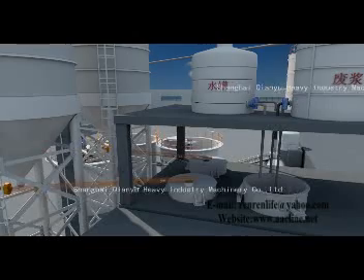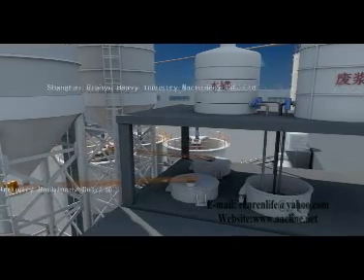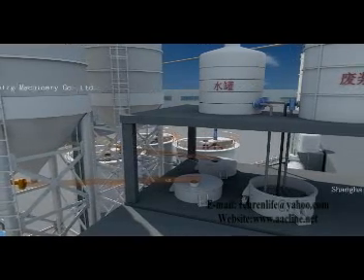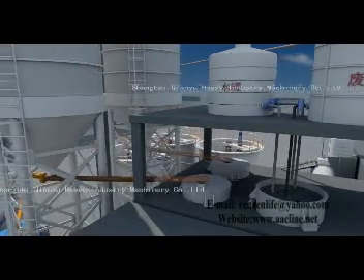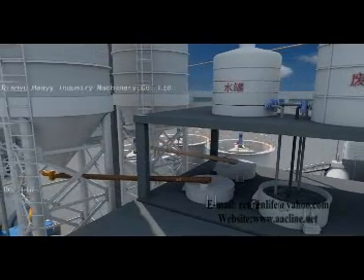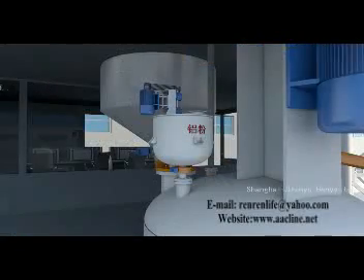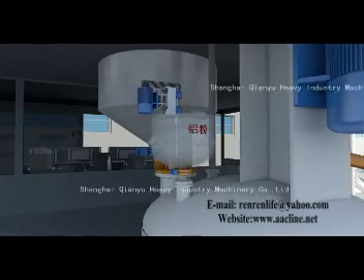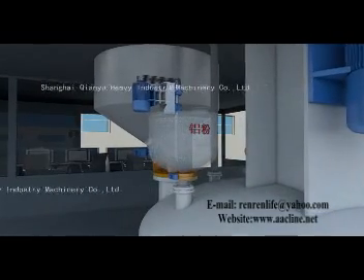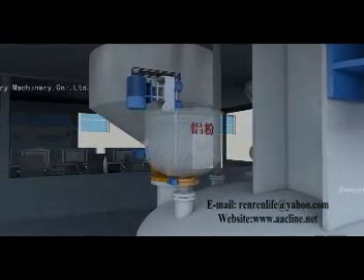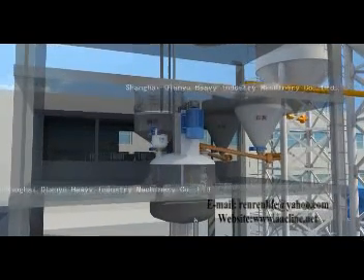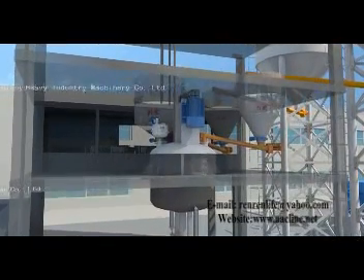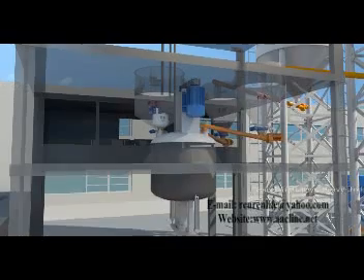The original and waste slurry in the storage tank on the batching building will be transported to slurry scale tank through pipes. The lime and cement will be transported to the powder scale silos by screw conveyors. The measured aluminum powder will be made into suspension liquid in the aluminum mixer. After metering, the slurry, lime, and cement will turn into the pouring machine to be mixed with high speed.